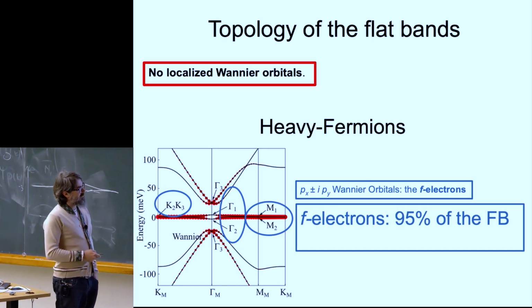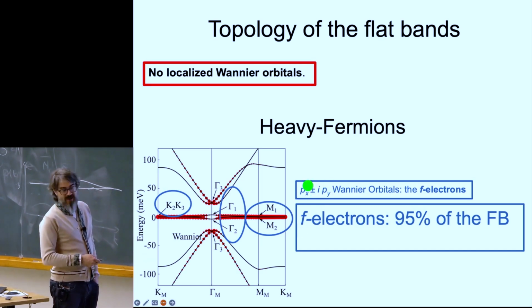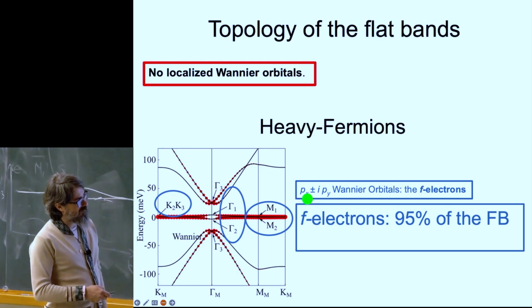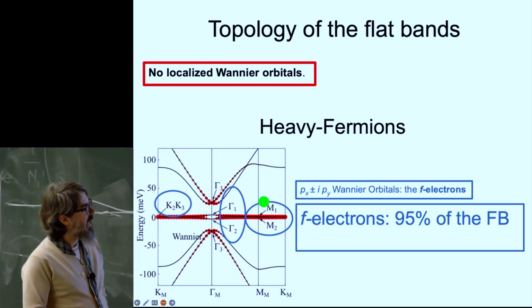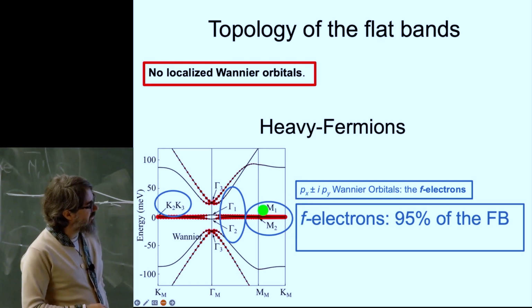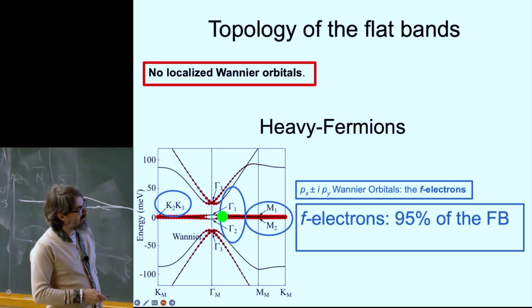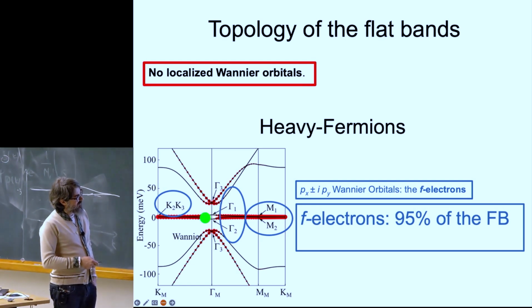And then you have 2 orbitals per unit cell. Their symmetry, even though I'll call them F electrons for abuse of language, is px plus minus i py. These orbitals give you the same eigenvalues at the K point and at the M point. They give you different eigenvalues at the gamma point, but the gamma point has the flat bands. In fact, they give you the same eigenvalues as these remote bands, which are within the reach of the Coulomb interaction. So then you ask, how much of these super localized orbitals are contained in these bands? Now, at the gamma point in these flat bands, you cannot have any of them.